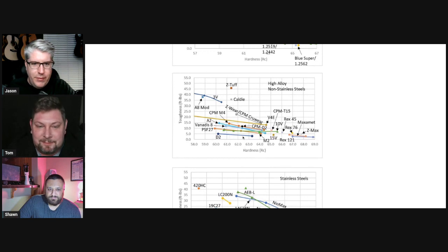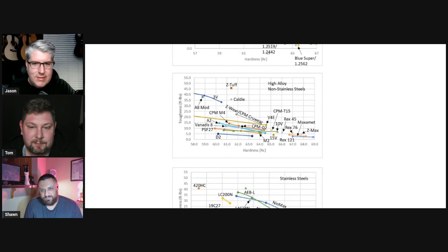So we're going from the range of 5 to 4 all the way up to maybe 12 on the toughness scale. So a comparable steel would be Vanadis 8. It's actually tougher than 10V. It's not quite as tough as 4V, V4E, excuse me. It's in the range of M4. So CPM D2 is a significantly tougher steel than D2, and it's courtesy of that particle metallurgy process. That's really what I wanted to show everybody so they understand what that CPM thing is. I think everyone knows the initials, but they don't really know why it's better and what effect it has.